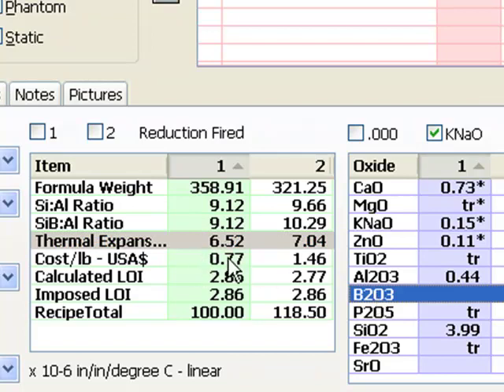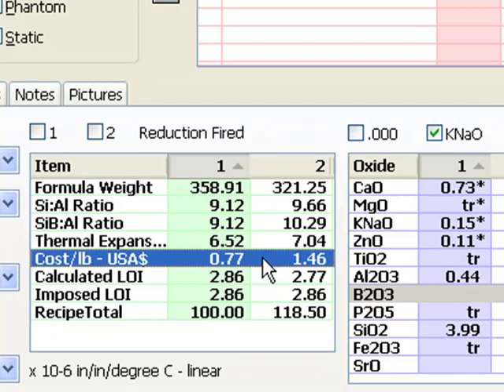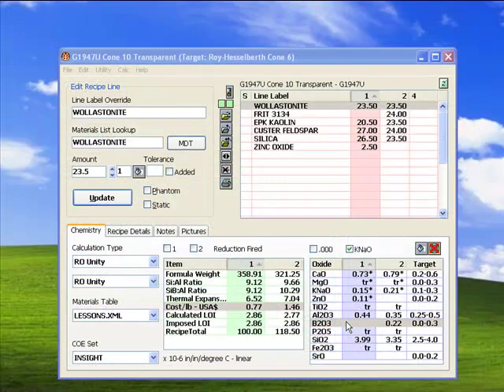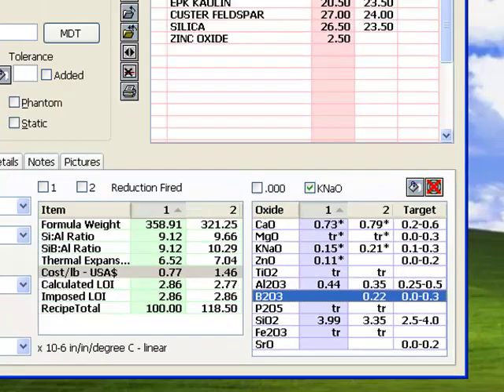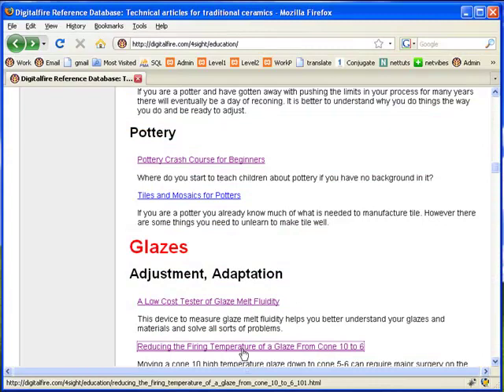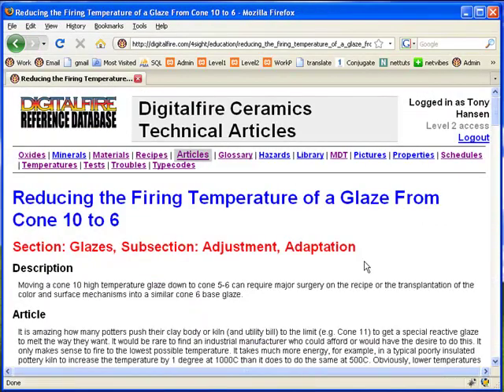Notice also that the cost is up — that's expected, since frits are more expensive. You can set costs of your individual materials using the materials or overrides type codes dialogs. So the secret to reducing the firing temperature of a Cone 10 glaze is to add boron and leave the rest of the oxide amounts unchanged. There's no way you can do that without ceramic chemistry. The article from the Digital Fire Reference Library says that sometimes it's better to identify the color, opacification, and variegation mechanisms and then transplant these into a Cone 6 base glaze of similar properties to the Cone 10 one.